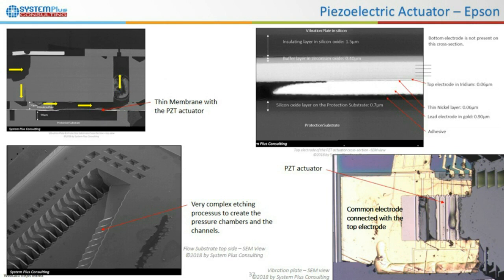The PZT actuator is probably manufactured by a sol-gel solution with spin coating deposition, and you estimate that this deposits a thickness of 1.5 micrometers, probably in 5 spin coating steps. But it's not the only unique characteristic of this printhead. The PZT is not the same.